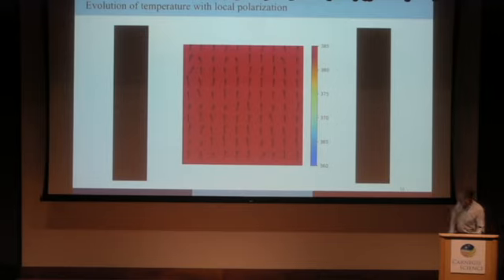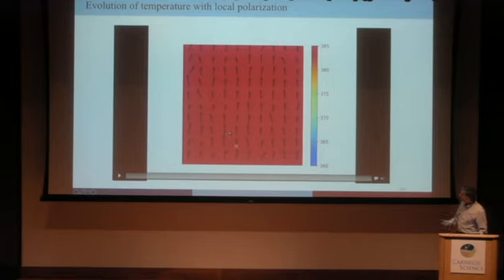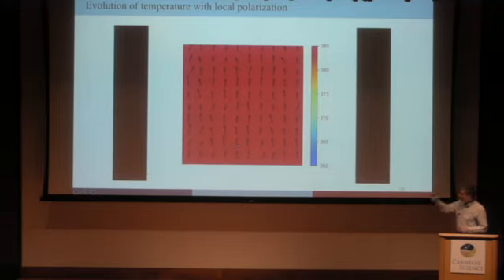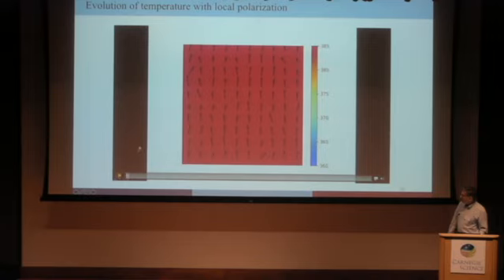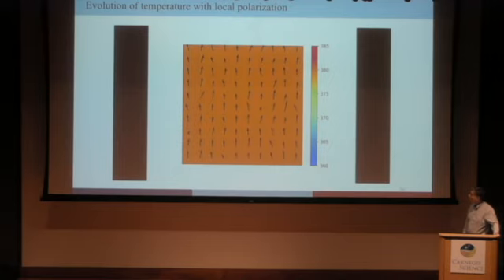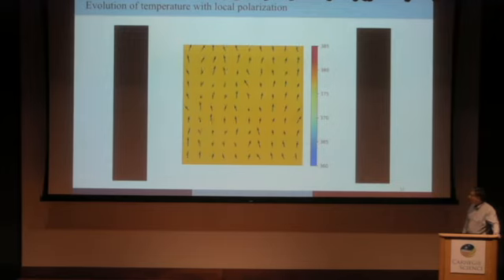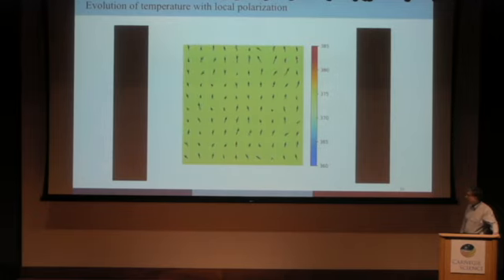Okay, and so here is a short but nice movie of this. This is the case of tetragonal barium titanate. Do you see the dipoles are pointing up, but the electric field is applied along the horizontal direction. Okay, so they're undergoing thermal motion, but then some of them are starting to rotate. You can see that there's just a greater disorder in the dipoles, but some of them are visiting, being 90 degrees away from the original direction.